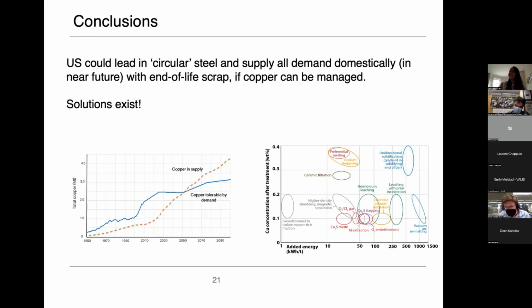But I did find it very interesting to come at it from the copper industry side, where there is iron in the copper ores, and the way that's dealt with is just to oxidize the iron completely, and it becomes an iron silicate slag that can be used for aggregates or low value things. But we are thinking that it is interesting you can get this metallic iron out of that mineral with our new process.